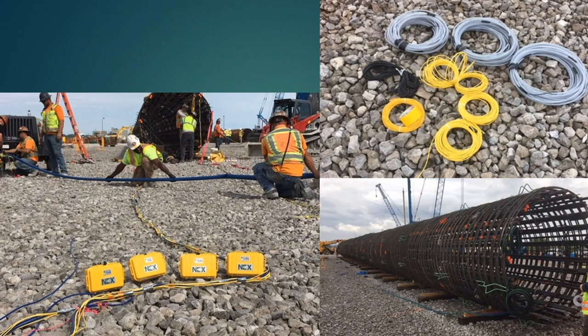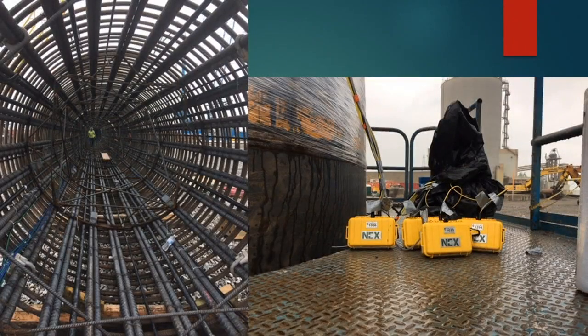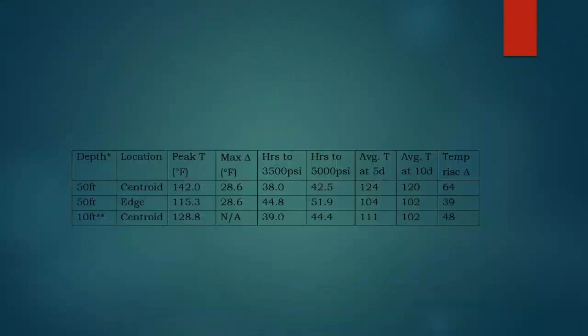I think these were 100 and something feet deep. We needed to monitor from about the midpoint on up, and so we had sensors that were placed all throughout this cage, and then the sensors actually came up and over this collar here. And if you can see where my mouse is, we've got our devices sitting there recording all of this. And so when you record all of this temperature, and it may be a little difficult to see, this is some of the summary data that we were able to collect from that particular test pour that we did,